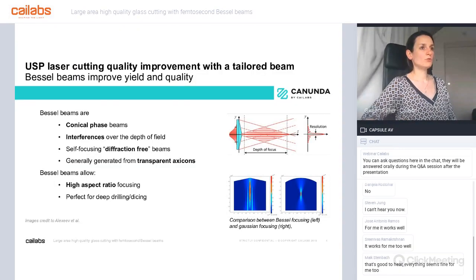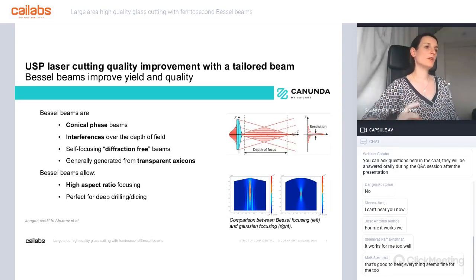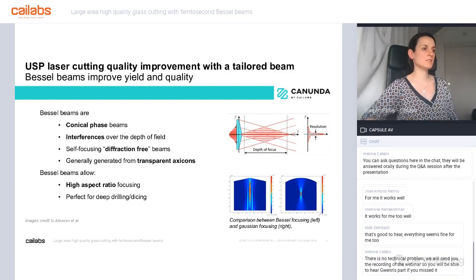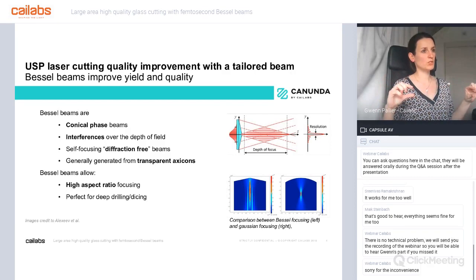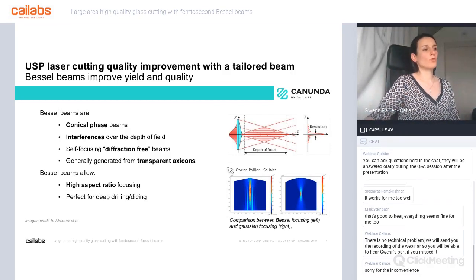So how to cut glass? Arndt did explain that quite well already, and you could see on his scheme that one of the interesting ways to cut glass is to drill holes through the whole thickness of the glass. So a good way to do that with a laser is to have really high aspect ratio beams. It means that you want to have a really long beam which will show quite small widths. So the classical way to do that is to use an AXICON.